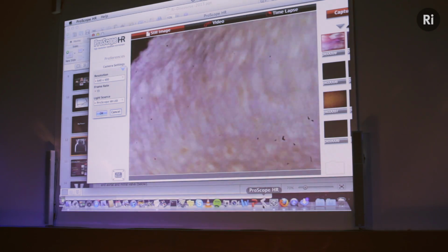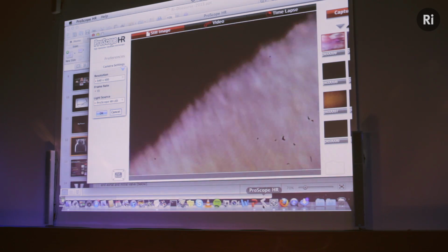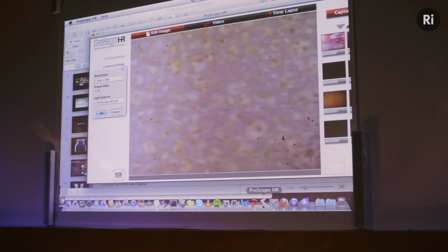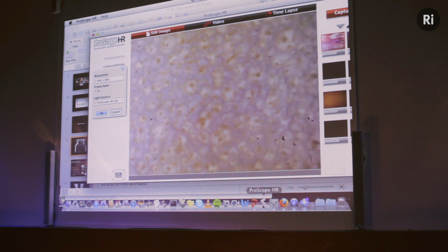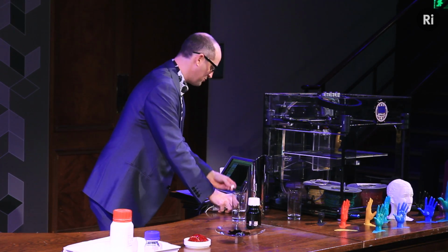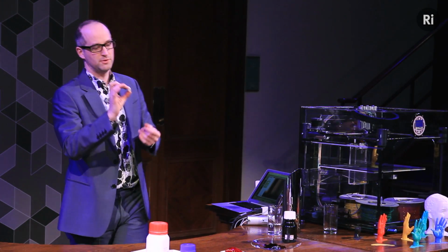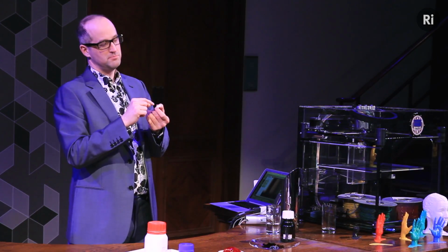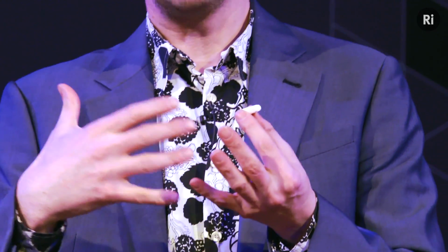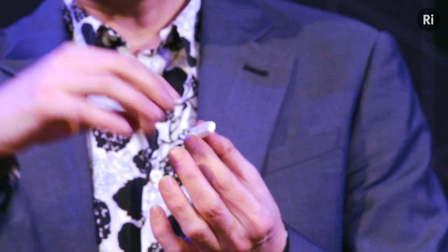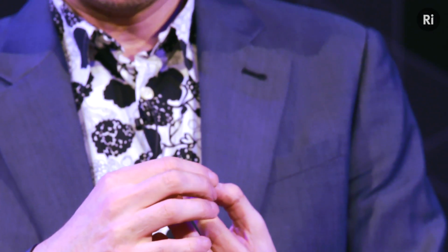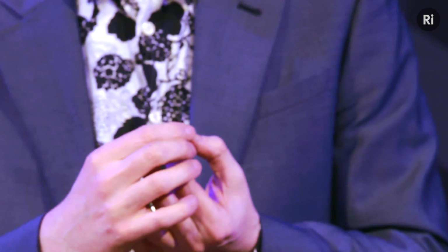Okay, here it is. It's a very porous material, and white. I know it doesn't look like a glass, but it's an amorphous structure, and technically it is a glass. He found something very remarkable about the properties of this material: if you implant this into the body, or if you put stem cells onto it, those stem cells will develop into bone cells. In doing so, they'll infiltrate the material and replace it with bone. It's kind of a miracle that this is possible.